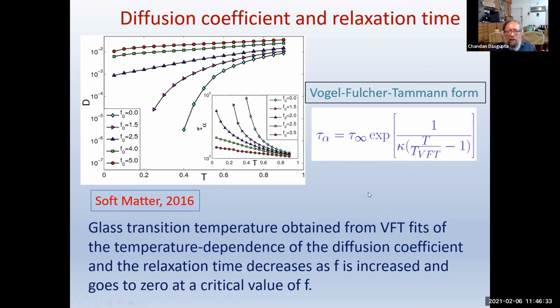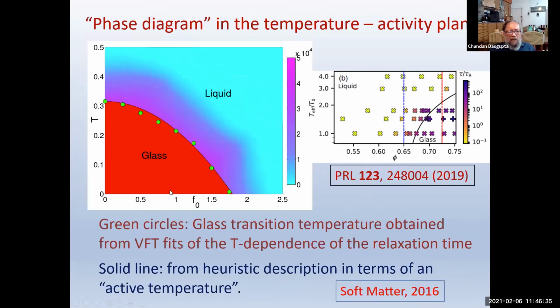So from this, one can get some kind of phase diagram. Here is temperature, and here is the strength of the activity. When there is no activity in the passive system, there is a glass transition temperature, which is about 0.3 in reduced units in this system. But this glass transition temperature decreases as we turn on the activity, and eventually, beyond a certain value of the activity, there is none. It's always a liquid. There is no glass phase at all.